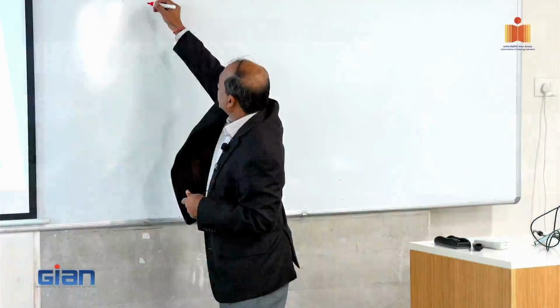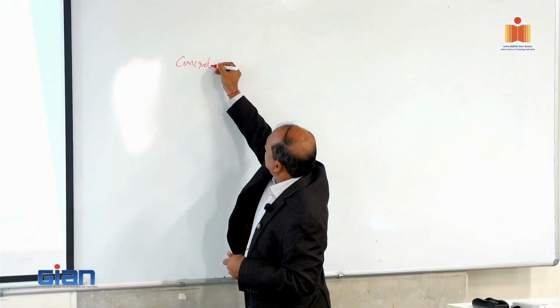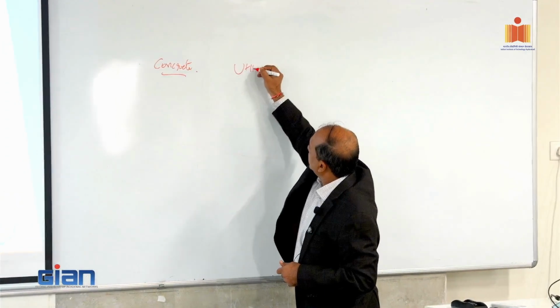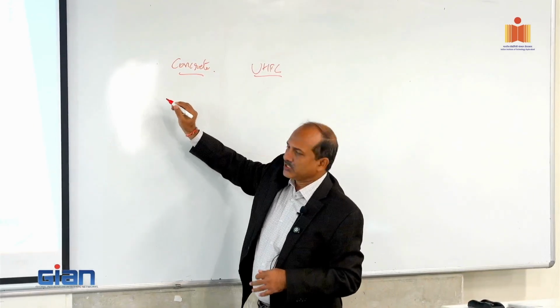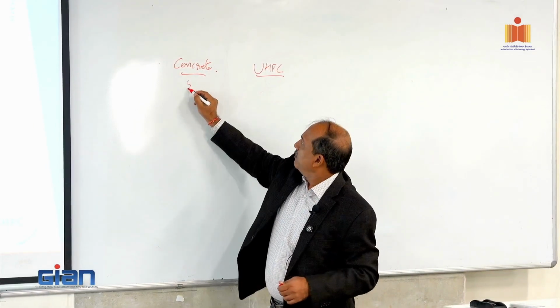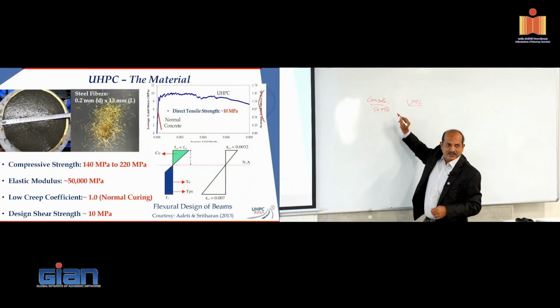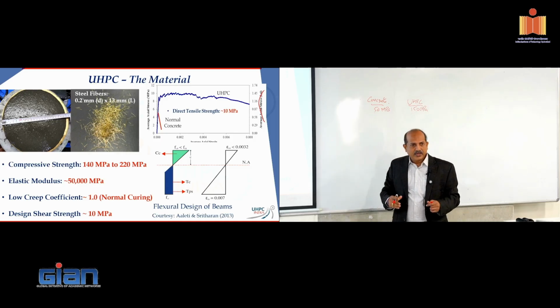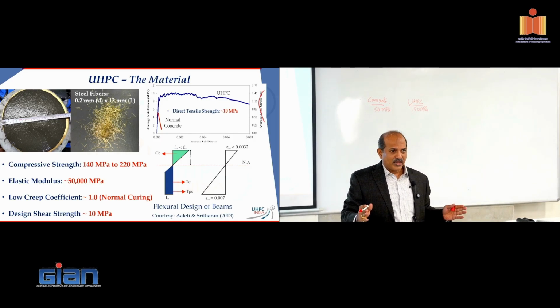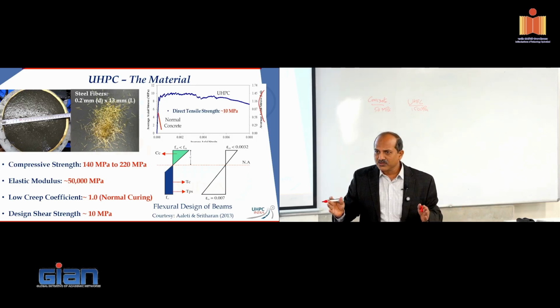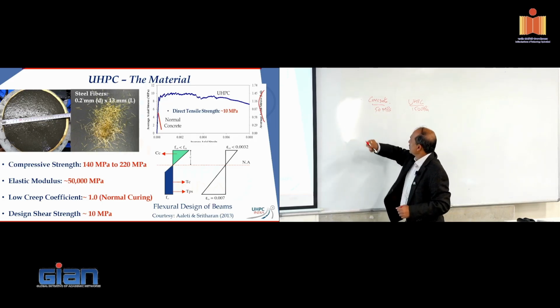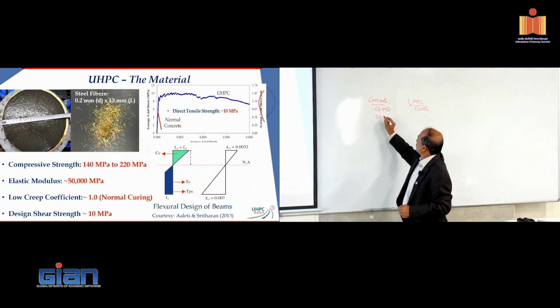If I take concrete and UHPC side by side, I'm going to put some numbers over here in terms of compressive strength, right? 50 MPa right there, and 150 MPa right there. Typically, you would say I get 2/3 of my compressive strength, initial strength, and I can do my post-tensioning or pre-stressing. I can release my pre-stressing, right? So I'll put some number over here. Initial, at the jacking force, you need about 30 MPa right there.